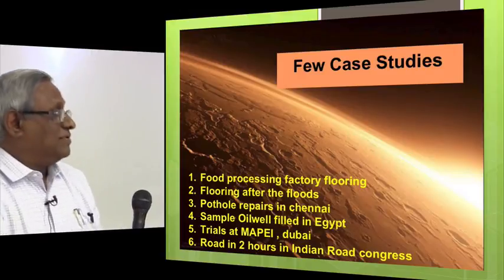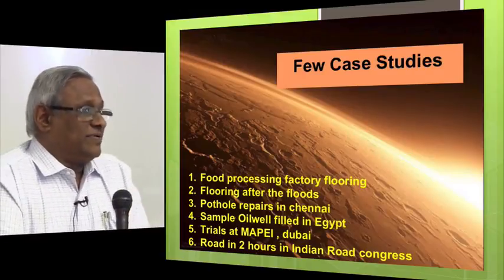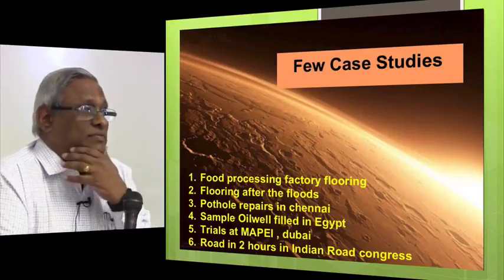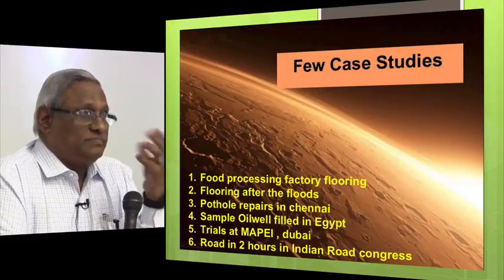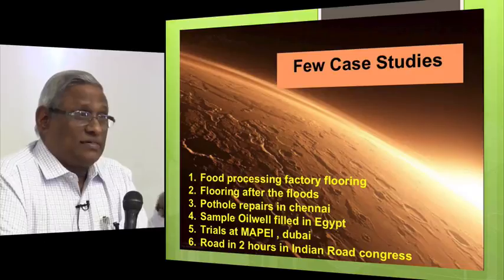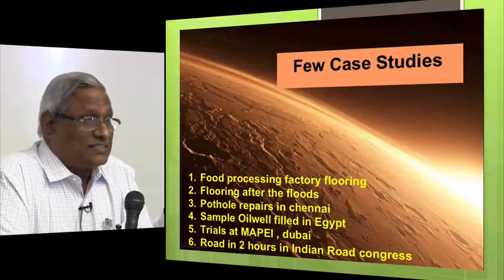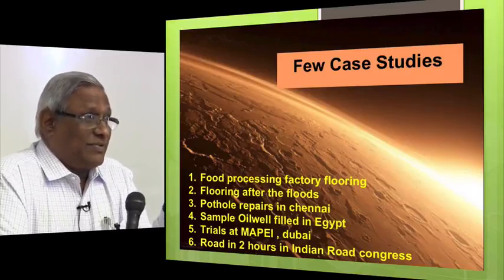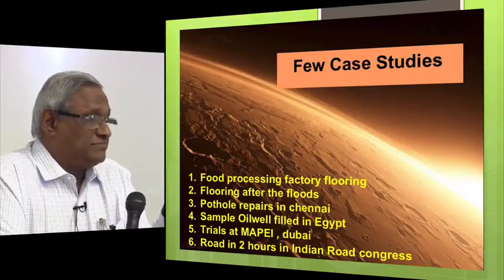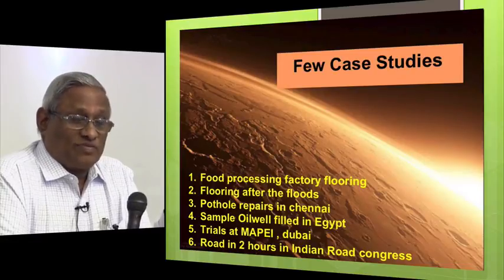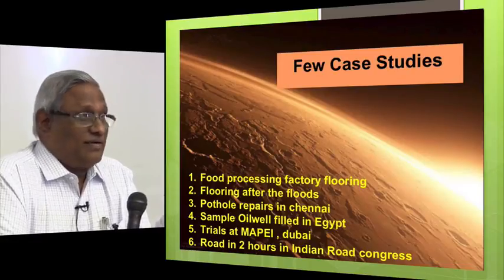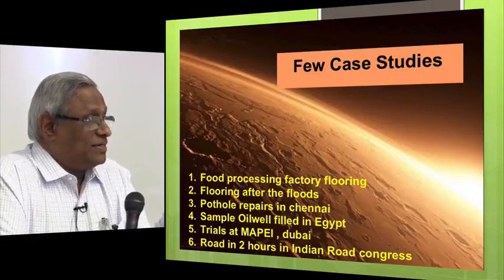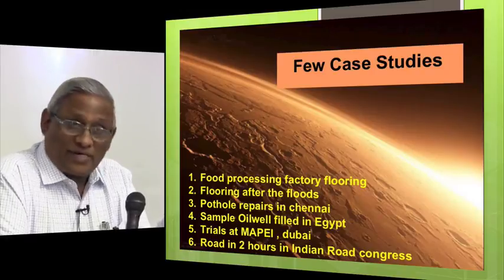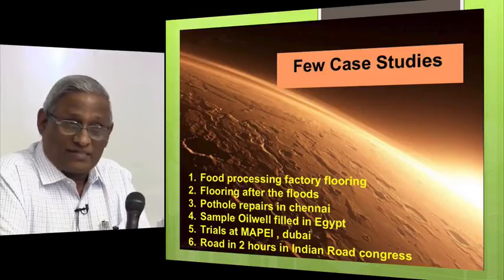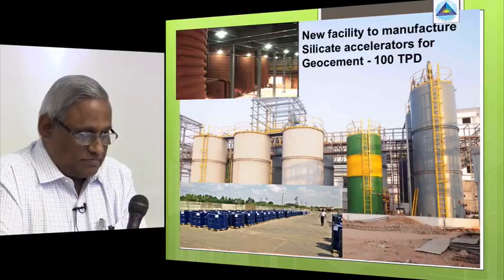oil well. See, in western Egypt, there was an oil well, and they were trying to put oil well cement on these things. They were not able to arrest it because the gas was coming out at 200 degrees centigrade. So it was very difficult. So from the Egypt factory, we asked them to formulate our Geocement, and then we took it, and a sample well was plugged, sealed very well.